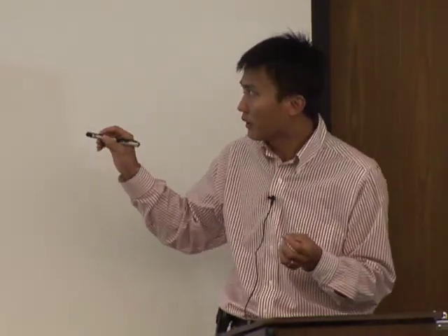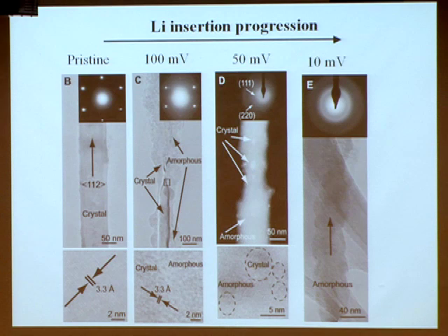We have done a lot of detailed studies to look at structural change, to look at what's happening in the interface, but I'm not going into the detail of that. Let me just show you the most important thing you see in silicon used for battery electrodes. That is the structural transformation process. The nanowires we make after the synthesis are single crystal nanowires. You look at this under a transmission electron microscope. This is a crystalline lattice. You can see it's a single crystal. Electron diffraction shows this spot pattern. That tells you it's a single crystal.